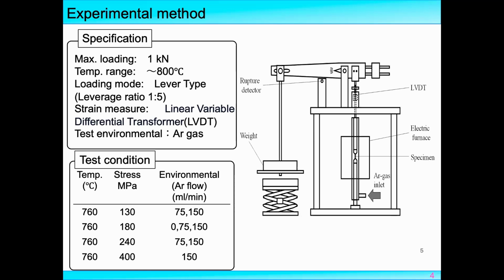And here gives the experiment method. This figure shows the creep testing machine we used. It is developed by ourselves, and the specification is given here. The maximum loading is 1 kilonewton, and the test temperature range is from room temperature to 800 degrees. And the loading mode is lever type. The ratio is 1:5. We use the LVDT to measure the strain during creep test, and the test condition is given here.